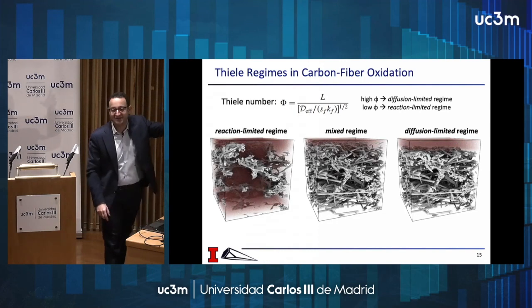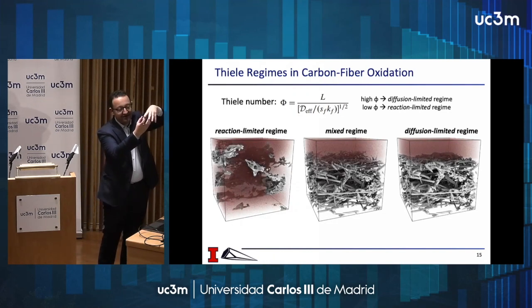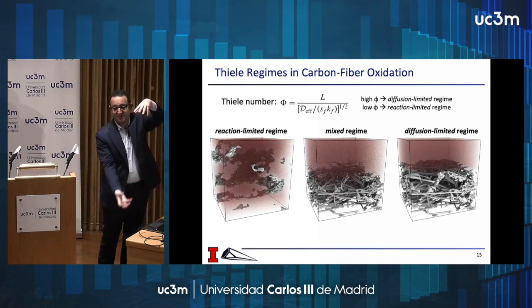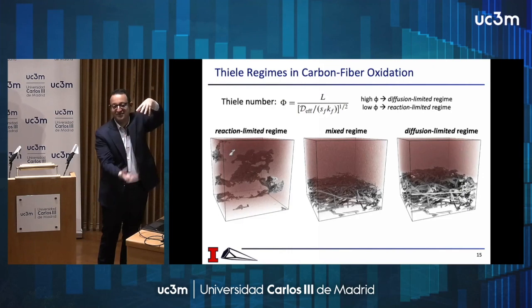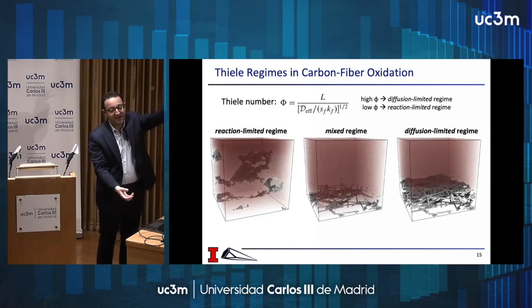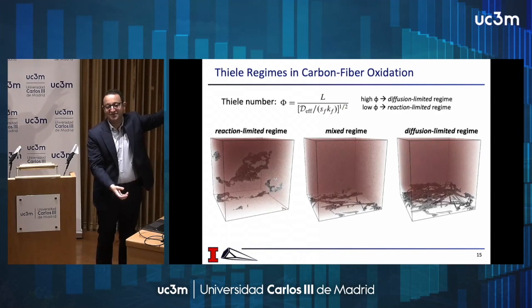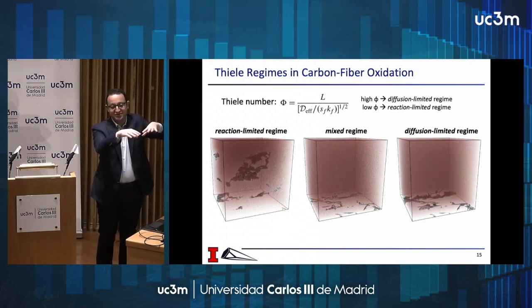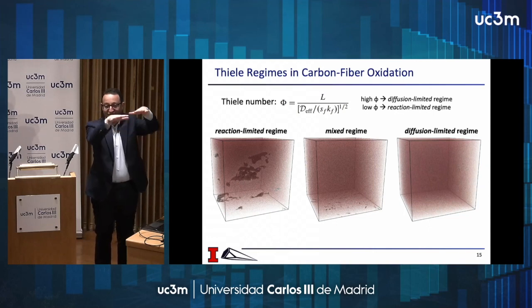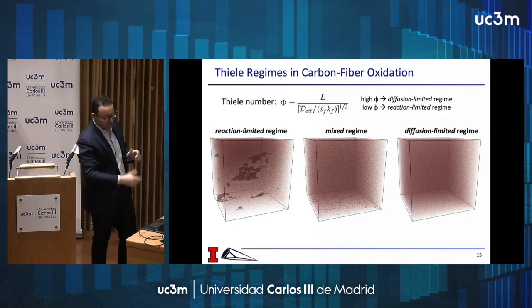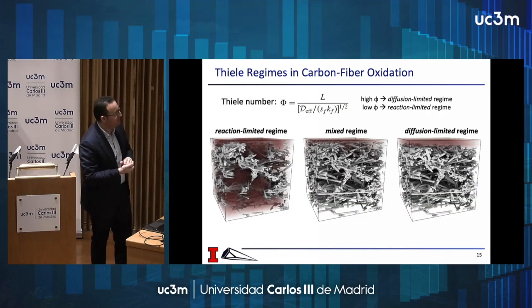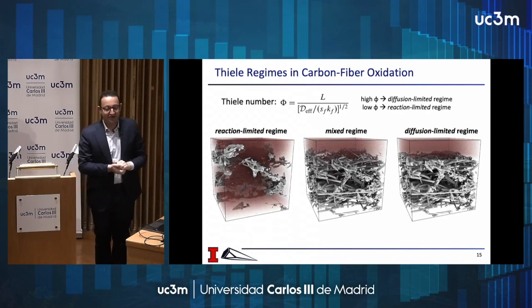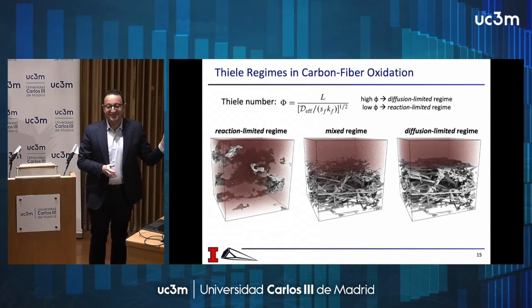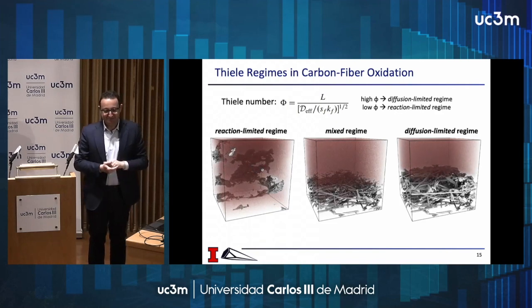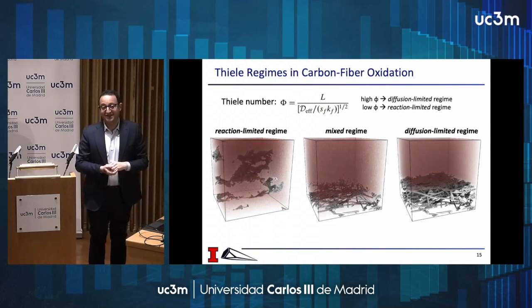A reaction-limited regime is when the reaction is slow, and so the particles can penetrate inside the porous medium and decompose the material in depth. On the other hand, the opposite asymptotic limit is the diffusion-limited regime, where the oxidation process is very fast, so it happens all at the surface and the material recesses. So oxidation is very fast and diffusion is slow, and then in reality you would probably have something in between. So this is a simulation, taking the real image of the material and applying a model to it.